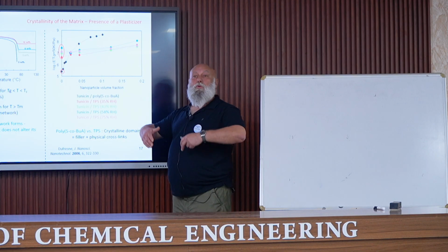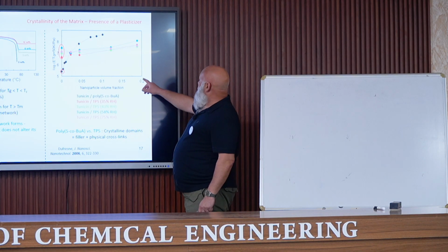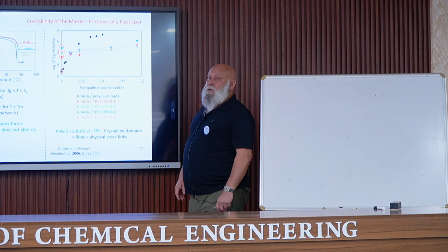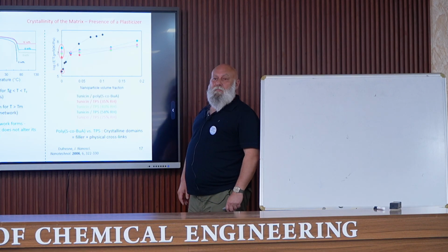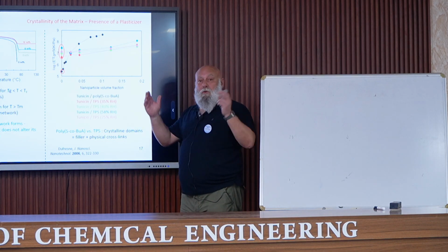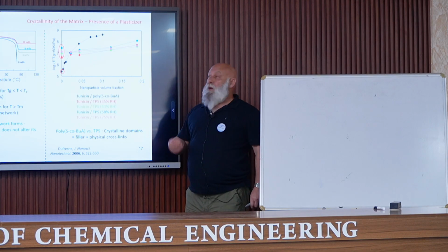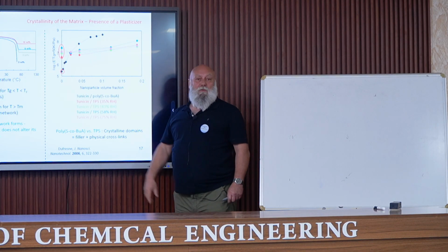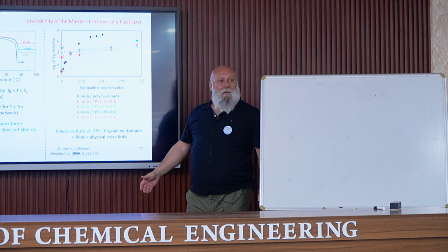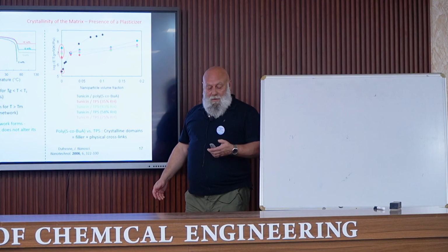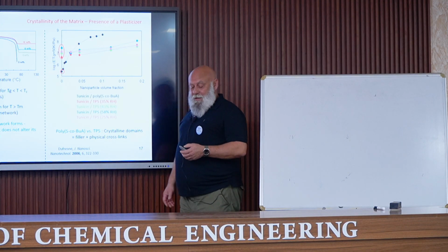She used a huge amount of nanocrystals. You can see 18% by volume, so it was 25% by weight. We never use so much. But even for this amount, you can see that there is no reinforcing effect. And again, you need to think about what happened.